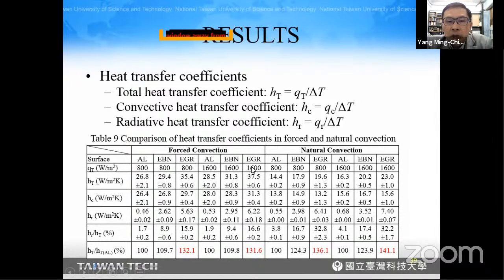And the difference between the 800 total heat transfer heat flux is a little 132 now, and the other one is 131. And for natural convection, the ratio is bigger, even bigger, for 800 watt per meter square, and the ratio increased from 100 to 136. And also for higher heat flux, it increased from 100 to 141. This indicated that in the case of natural convection, graphene loaded coating can improve greatly the heat transfer.